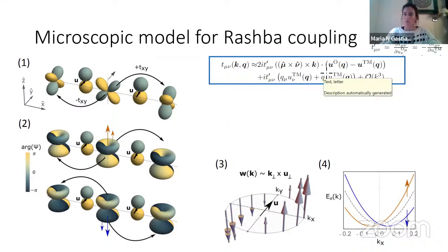So once you do this kind of expansion in U and expansion at small k, you get two terms for this process here, the interorbital process. The second term here would be a conventional coupling to longitudinal modes, which vanishes at q equals 0 as it should. But the first one here, which is proportional to this polarization, couples to the polarization waves, and it does not vanish at q equals 0.